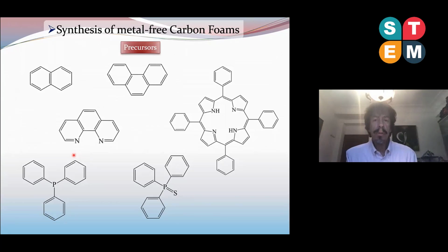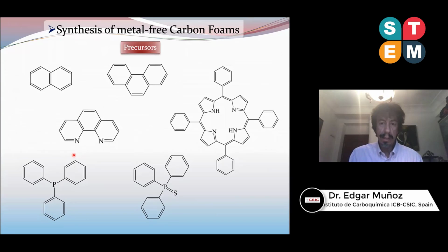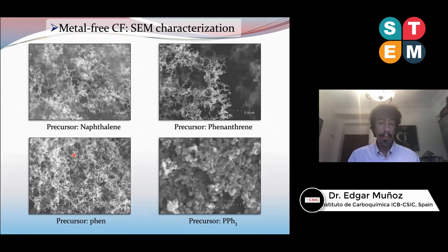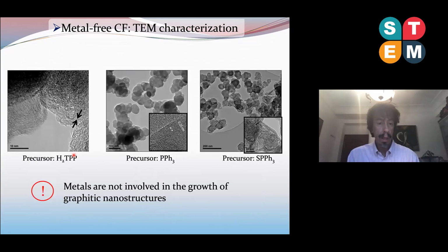We wanted to know more about the role of metals in the growth of graphitic structures in the carbon foams. So we irradiated different commercial organic compounds, polyaromatic compounds mainly, and we observed that all of these materials resulted in the production of this kind of foam-like nanomaterials. These materials consisted of amorphous carbon aggregates and ordered graphitic concentric structures. So metals are not involved in the growth of these graphitic nanostructures.